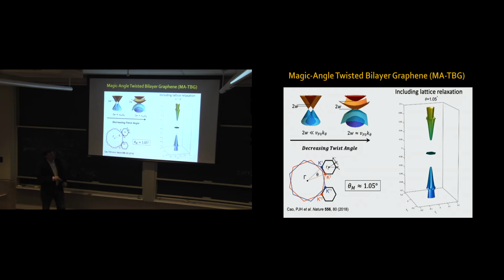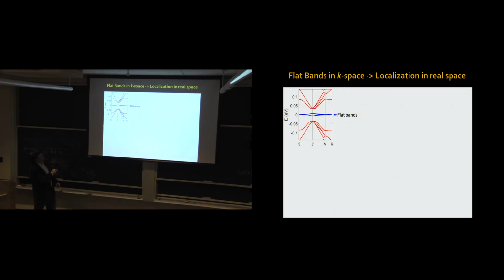So let me take a cut down that flat band there. This is the energy versus momentum for that. You can see this no longer looks like the linear Dirac dispersion of graphene. It looks like it's not 100% flat - there is a little bit of dispersion, but it's orders of magnitude flatter than the graphene dispersion. This says the Fermi velocity is orders of magnitude smaller than it was in graphene.